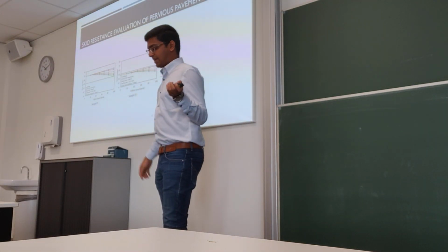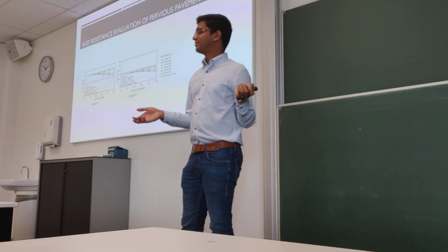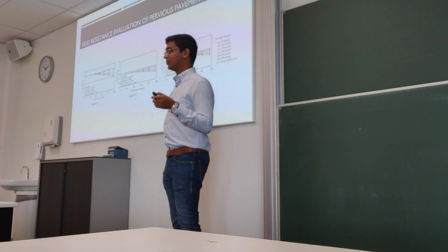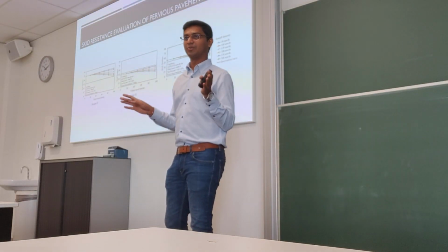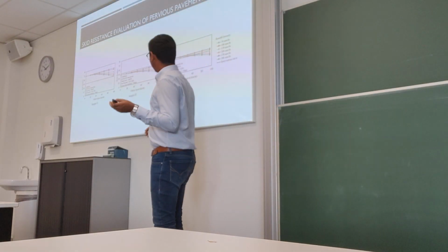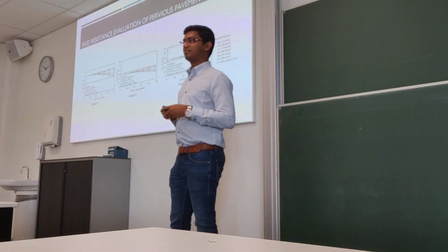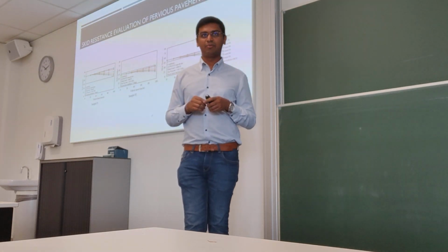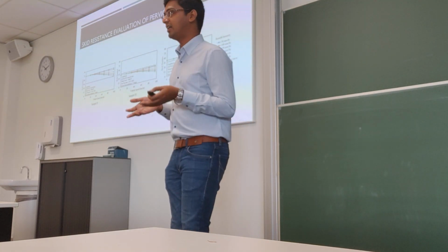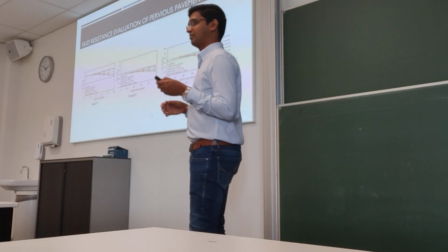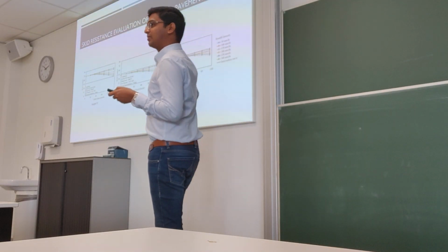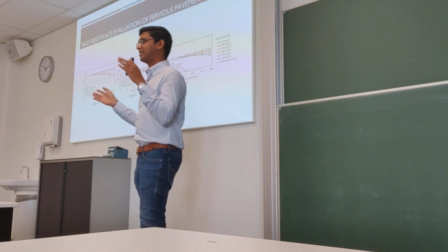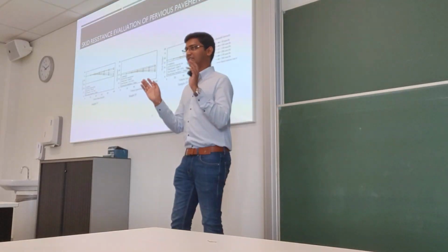We did the same for different road samples, and we found that some samples fail terribly. If you look at P2, we shouldn't even think about P2. It's a complete disaster. If you look at sample P3, it will behave well until 100 mm per hour rainfall intensity. If the rainfall is much higher, accidents are going to happen for sure. In that way, we can go forward with a new concept called variable speed limits. Based on different rainfall intensities, we can change the speed limits.